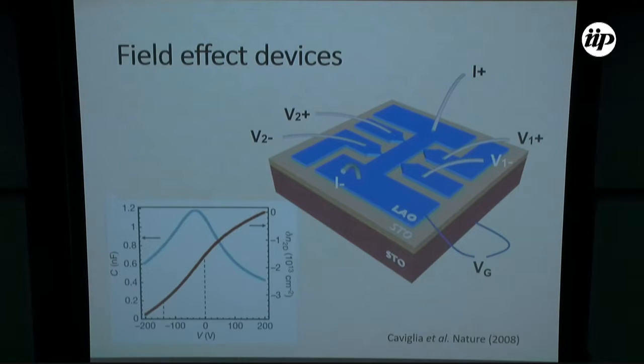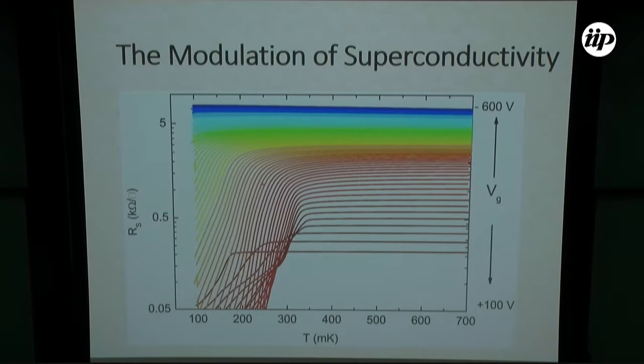So it's quite natural to perform field effect experiments, as you see here in a device, so you can measure transport in plane, and applying just a field across your strontium titanate substrate, you can modulate the carrier density by a relatively large amount with respect to the carrier density of the system, and so you can effectively modulate the electronic properties of the system. And if you look at low temperature at the superconducting transition, here you see the effect. So for the depletion state, minus 600 volt applied to the backgate, we see the system is in a weakly localized conduction regime. As we introduce carriers into the system, as we dope by applying positive gate voltages, we see superconductivity appears, TC increases, reaches a maximum, and then decreases as we dope the system further.